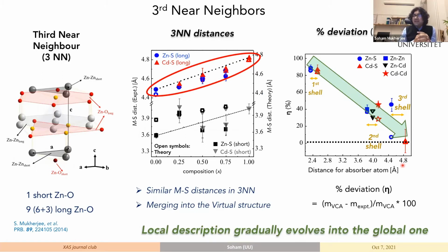And this is where XAFS comes in handy. It looks at the local distortions, which are non-periodic in nature. It's a process which doesn't require symmetry to be preserved, right? So diffraction would of course contain this information, but it will be contained in the diffuse background and not show up as a particular signal in the system. So an average description of the crystal would always be valid, and that is the reason why you get such sharp Bragg peaks. So your system is perfectly crystalline, but when you look closer, you will see that locally the symmetry is broken, and there's a fancy interplay of change of distances and angles, which match up and still hold the periodicity of the material.